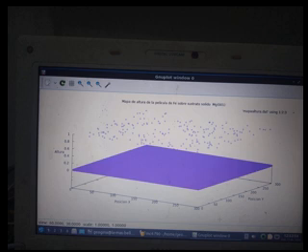the Curie temperature they got from their simulations matched up almost perfectly with what you'd expect from a 2D Ising model. A 2D Ising model, refresh my memory on that one. It's a theoretical model that's often used to study magnetism, specifically in 2D systems. So it's like a theoretical framework for understanding how magnets behave in two dimensions. Exactly. So their simulations for these super thin films lined up with what theory predicted for a 2D system. Pretty neat, huh? That's pretty solid evidence to support their claims of this dimensional shift.